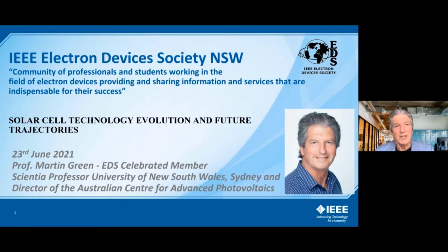So a lot of those technologies are ruled out. But there is a role for non-silicon technology in this stack cell concept, because you need something other than silicon to stack onto silicon that has a different band gap from silicon at least. So we explored all silicon approaches using quantum dots and things like that to expand the band gap, but it wasn't very productive. So I think you're going to have to find another compound semiconductor that has the attributes of silicon, higher band gap, and abundant, non-toxic, stable and efficient materials. So that's the big challenge facing photovoltaics, because there are many contenders out there, but none of them tick all those 4 boxes. Thanks for the question.